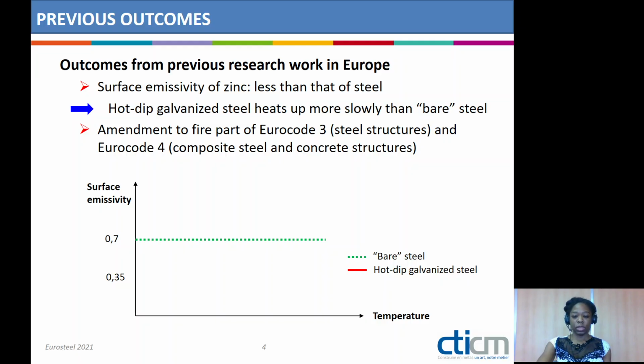However, if you have hot dip galvanized steel, you have a temperature of 500 Celsius degrees at which the value changes suddenly from 0.35 to 0.7. This is due to the assumption that at 500 Celsius degrees, the zinc coating has already fully melted. So you can see that the temperature rise of a hot dip galvanized steel member is quite less important than that of a bare steel member.